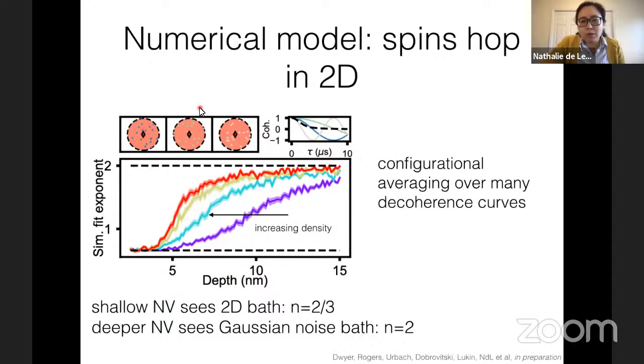Okay, so we can now just do numerical modeling of what happens if you're sampling these different geometric configurations at the surface, where they're in 2 dimensions. What we find from numerical modeling is that if you look at NV centers at very deep depths, where they see a large number of different surface spins, then you indeed recover this n equals 2. As you approach the surface, the NV center looks like it's part of a 2D bath of spins. It turns out the exponent should look like d over alpha, where d is the dimensionality and alpha is the strength of the interaction. So you end up with an n of 2/3. As you increase the density of the surface spins, you change the depth at which you see this transition happen. So this likely accounts for this funny exponent that we see.